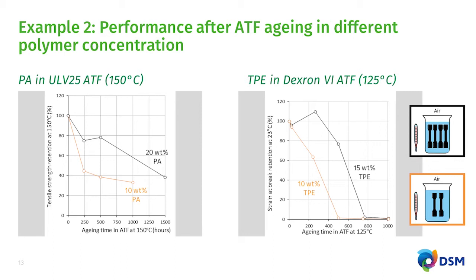And you can see actually when you use a lot of polyamide during aging, the tensile strength retention is reduced less dramatically than when you use less polyamide, in this case 10%. The same situation happens also, for example, if you are looking at aging of thermoplastic elastomer, TPE, as a function of aging time in ATF. In this case here, we plot the strain at break retention at room temperature. Again, the same story. If you compare the result between 10% TPE in oil versus 15% TPE in oil, the retention of 15% TPE is shifted slightly to the right-hand side in terms of aging time. So the TPE has longer lifetime.